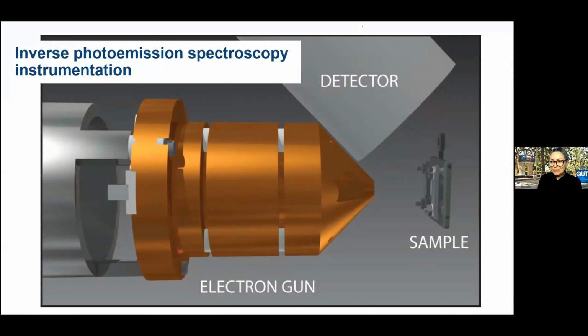This is what the instrument looks like schematically. Our electron gun is Stoffel-Johnson type. We've had a lot of trouble with our cathodes, and we've ended up with a LaB6 source in there, which gives us a ton of electrons and maybe a little worse energy resolution than we would like. Our detector is either a Geiger-Muller type, as shown schematically here, where we do vacuum UV detection inside the chamber. So these are the photons emitted after the inverse photoemission spectroscopy process. We can also detect in the visible outside the chamber.